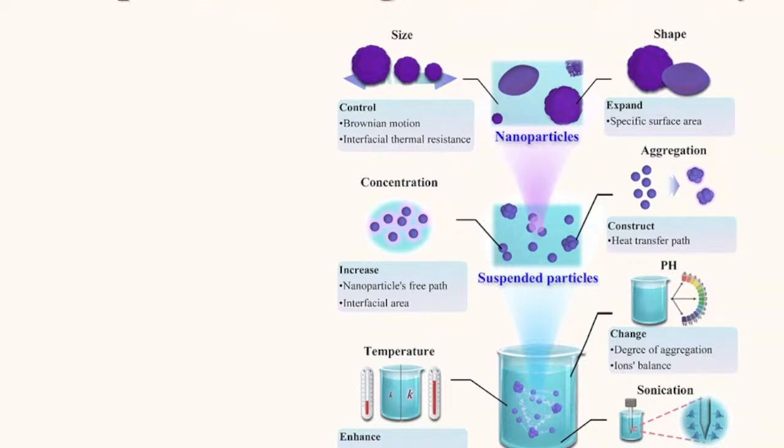And if you would like to adjust the pH, then we are going to change the aggregation ability of the solution of these particles. By increasing or decreasing the pH with respect to the base fluid, we would be able to create the surface ions, and also neutralize some of the cations or anions present in the solution, and accordingly we'll be able to make these particles suspended for a long period of time. Precipitation means it is going to get settled down; sedimentation and precipitation are synonymous. And suspension means they are going to be suspended.